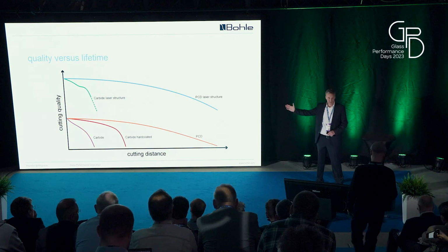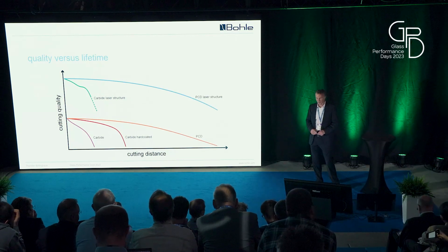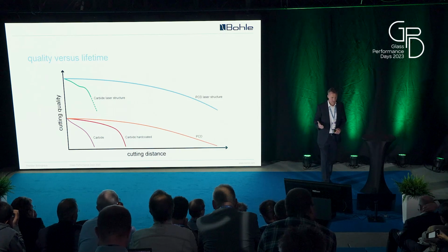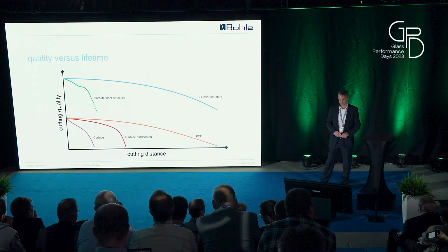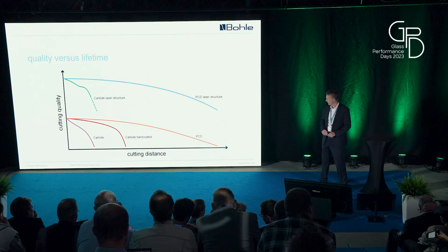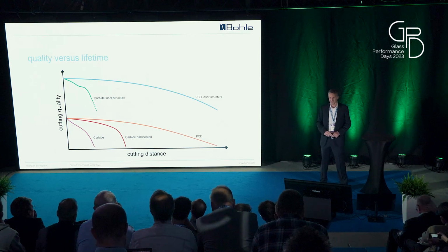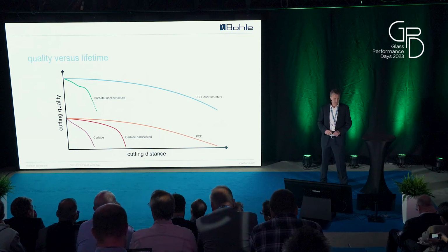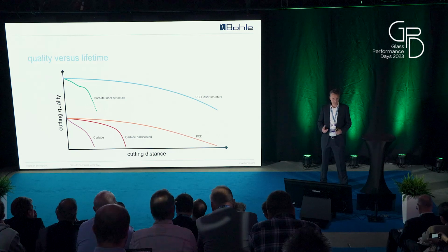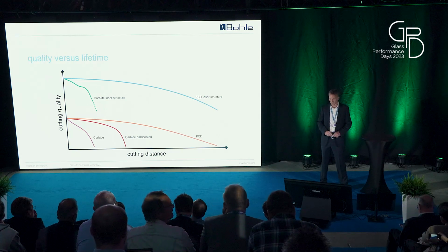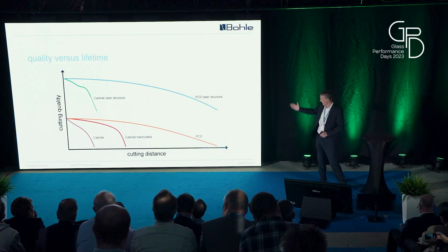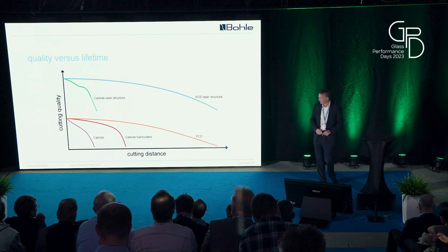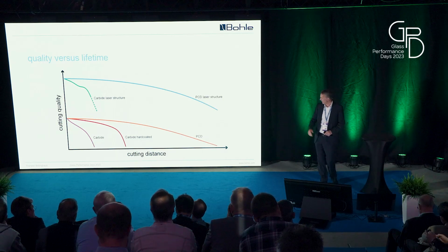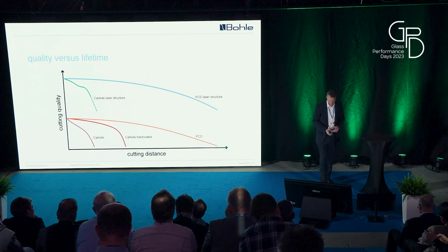It has a higher lifetime, a little more than the normal carbide wheel, because you need less cutting force, and less cutting force means less wear. Yes, but it's not a lifetime question. Using this type of wheel is a question of having completely different cutting properties and getting completely different results during the cutting of your glass. And for sure, if you combine the material and the laser structure, then you get the PCD laser structured wheel.